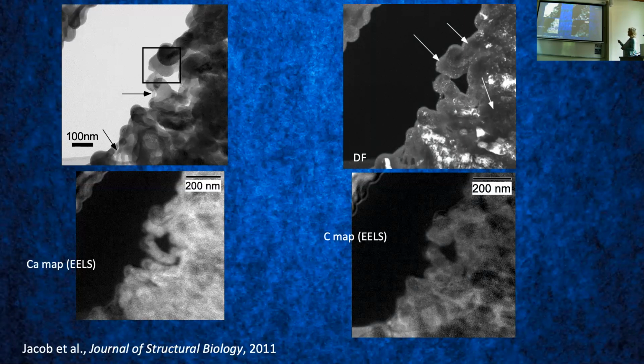So we took a dark field image, which shows you which areas are crystalline and which ones are amorphous. Everything that lights up in white here is crystalline. These areas, however, do not light up. So there are, in fact, amorphous calcium carbonate. There is calcium carbonate as shown from the calcium map, which gives you a very clear signal for calcium carbonate. And the carbon map shows you it's not enriched in carbon, so we're really looking at calcium carbonate.